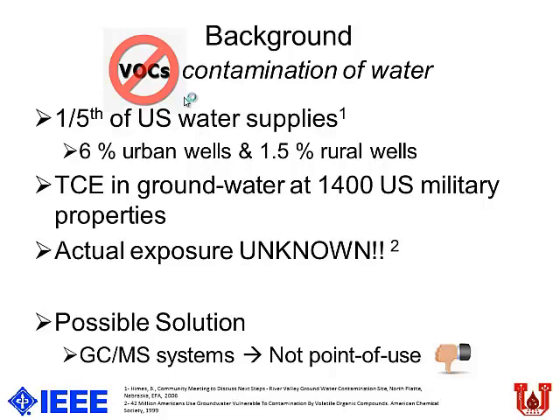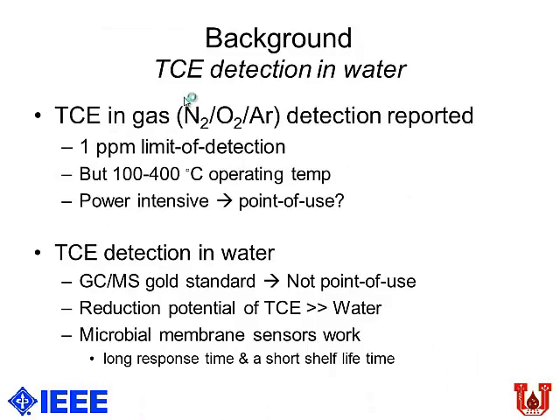So that's why we need some kind of handheld point of use sensor, which you can just take to the middle of nowhere and test water samples. For trichloroethylene, there's been some existing work in sensing, mostly for atmospheric sensing. It's been found in some paints that are used indoors. So they've been looking for trichloroethylene in gas samples, basically in nitrogen, oxygen, and argon as a carrier gas. A few of them have reported limits of detection down to 1 parts per million. But the operating temperature of these sensors is 100 to 400 C, which means they are power intensive. It's hard to make them point of use. For trichloroethylene detection in water, again the gold standard is GCMS, which is again not point of use.